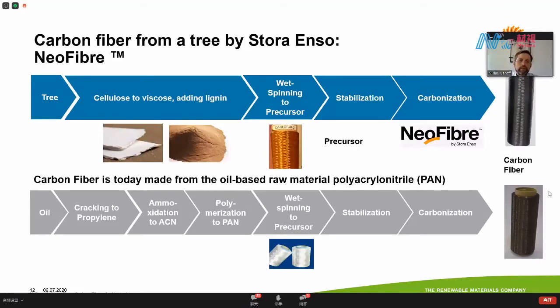So how do we do this? Let me first explain how carbon fiber is made today. If you look at the lower part of this picture, it shows the process scheme of today's carbon fiber production. 98% of all carbon fiber is made from an oil-based raw material called polyacrylonitrile, PAN. Starting from the oil, propylene is obtained in the steam crackers. This propylene is then converted to ACN, acrylonitrile monomer. And this is the main building block for making the precursor. The ACN is then co-polymerized together with other co-monomers to give the PAN polymer, the polyacrylonitrile polymer. And this is then dissolved in different solvents such as DMSO or DMF to give the spinning dope. And this spinning dope is then spun to a precursor using wet spinning or air gap spinning.